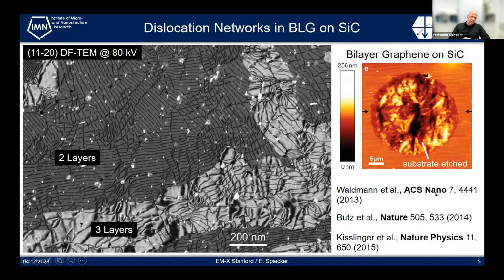We started back then investigating graphene on silicon carbide. You can grow graphene on silicon carbide by removing the silicon so that the carbon remains on the surface and forms a graphene under certain conditions.